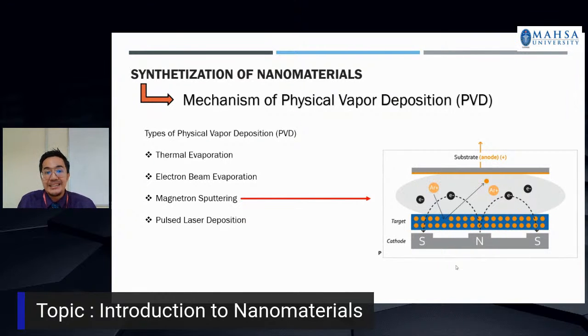So once the argon atom flows inside the plasma, it will be ionized. This ionization will create the argon plus and also the secondary electron. So this argon plus will bombard our target material, and then some of the target material will be vaporized onto the substrate, and this will repeat. The argon plus will recombine back with the secondary electron, become argon atom, and it will be ionized back into argon plus and secondary electron. It will be repeated until the whole substrate has a thin layer of nanomaterial.